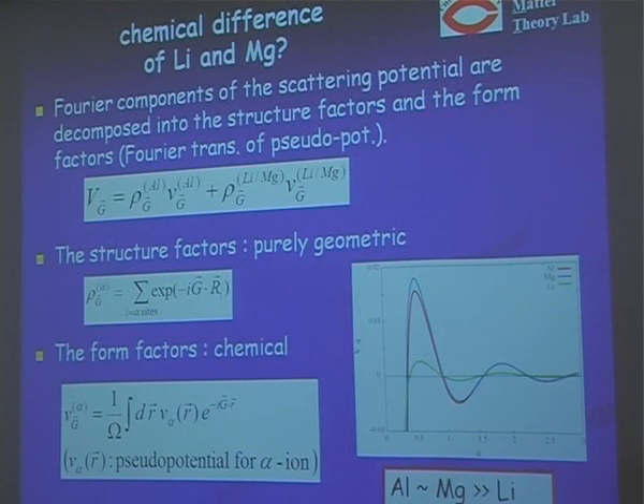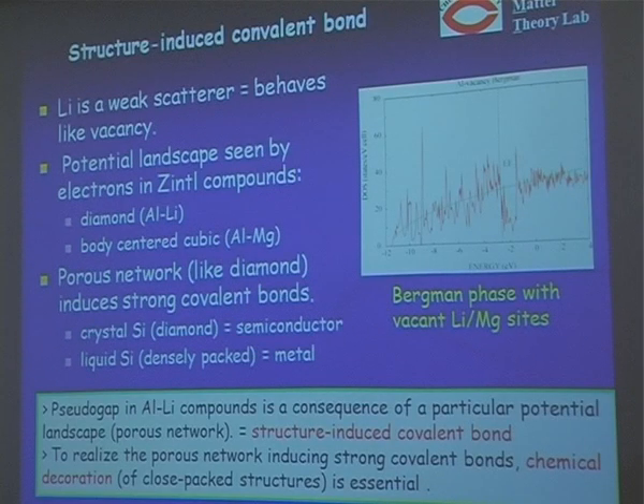And magnesium scatters electrons as strongly as aluminum. So that's a difference. Okay, so again, lithium is a weak scatterer. So that means that lithium behaves like a vacancy. So then the potential landscape seen by electrons in the Zintl phase is the diamond for the aluminum-lithium case, because aluminum is placed on a diamond sublattice. But in the case of aluminum-magnesium, the potential landscape is for the BCC lattice, a close-packed structure.